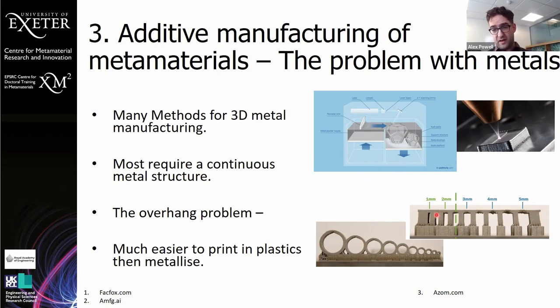So if you have something coming across at too steep an angle, at too long a distance, it kind of starts to not be supported by the powder beneath it, and you start to get crumbling and cracking in the layer, and it can wreck your prints. So actually, in terms of structural stuff, this is the real problem. In terms of making metamaterials, it's kind of easier to print things in plastic and then metallize them to avoid this, because there's plastic printing techniques which can be more robust for this overhang problem.